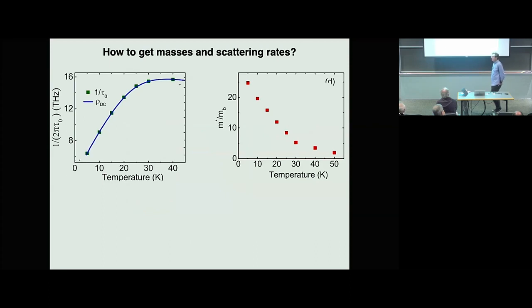Yes. But you have data for specific heat. Yeah, I didn't plot it on top, but it's roughly on top. The mass enhancement in the system goes up and goes down as a function of temperature. Part of the issue is that the mass measured here is a ratio to the band mass, and we've made an assumption about the band mass, based on LDA calculations. The heat capacity would typically be expressed in terms of the bare electron mass, but within the same band mass, with these kinds of uncertainties, the numbers are within 30% of each other. But I wouldn't say anything about the functional forms, if that's what the question was about.